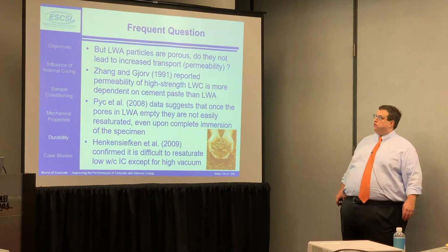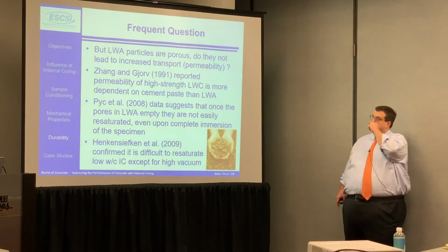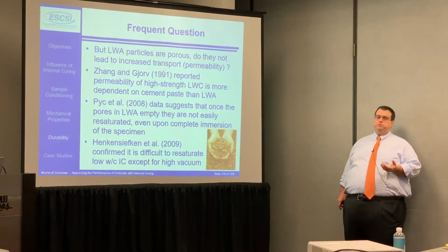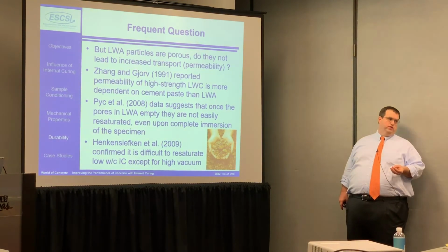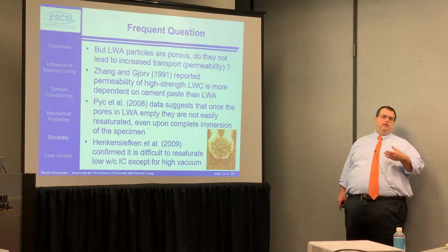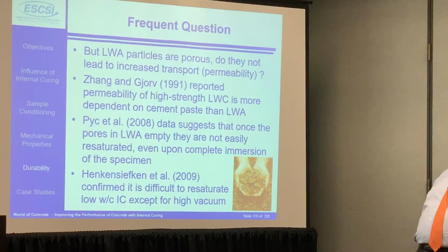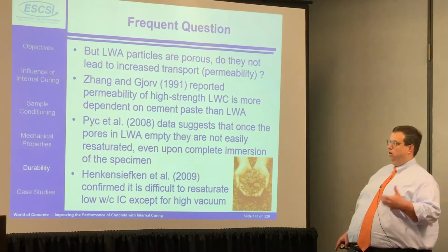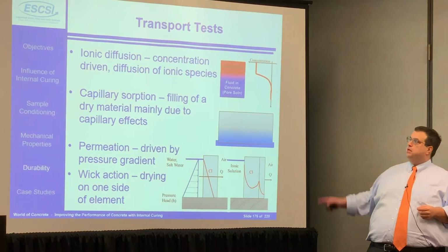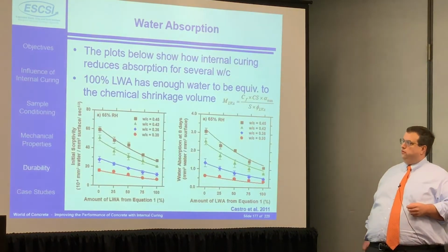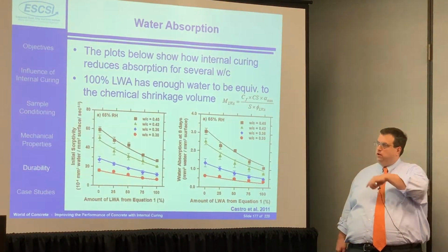Right? A lot of frequent questions we get. Are the particles porous? Do they increase permeability? Frequently no, because they are very hard to get resaturated with water, and essentially things only move through water in the system, so they essentially become relatively unimportant for the transport property. It's very difficult to resaturate them. We'll get into a couple of the different transport tests, but I guess what I want to talk about here